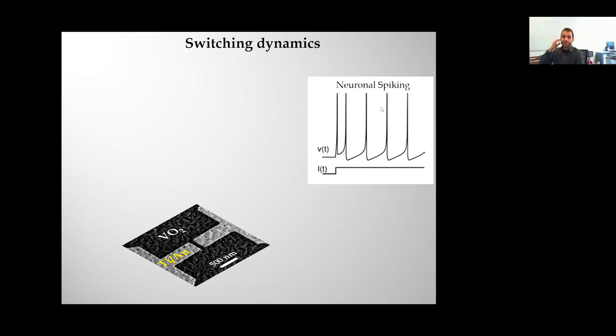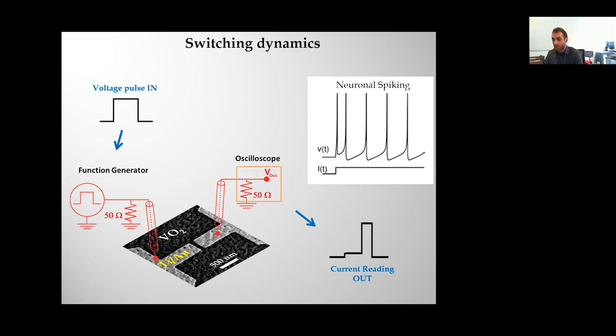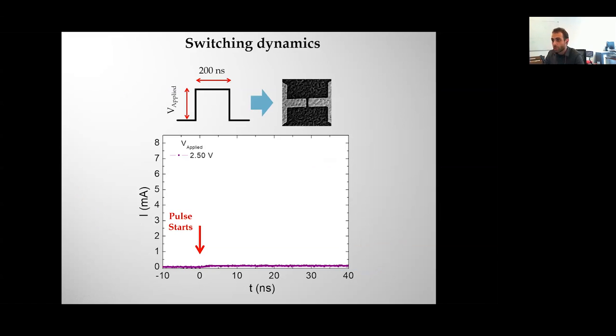So it's really important to understand in the nanosecond timescale, things like how fast does your material go when you apply a voltage from insulator to metal? How fast does it go back into the insulating state when you remove the voltage? So to carry out that kind of experiments, we use a high-speed probe station, and we send voltage pulses using a function generator to our device. And then we use a low impedance oscilloscope to take the current reading and see what is the dynamic response of the device. So this is what I'm going to show you here.